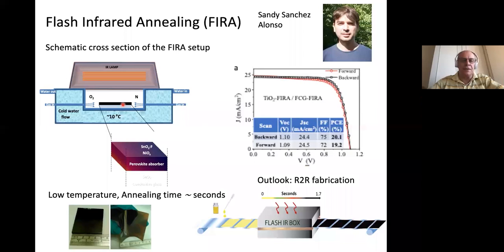And Sandy Sanchez, as a postdoc, has shown that he can get more than 20% efficiency. And by varying the flash time, how long you expose to infrared light, how long between the flashes and so on, he can control the morphology. And he can also sinter TiO2 films with UV light in the same chamber. So this is something which we think is suited for roll-to-roll fabrication, and it's something we are developing further.